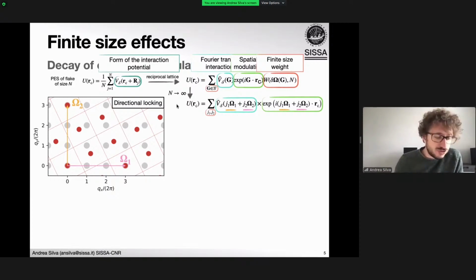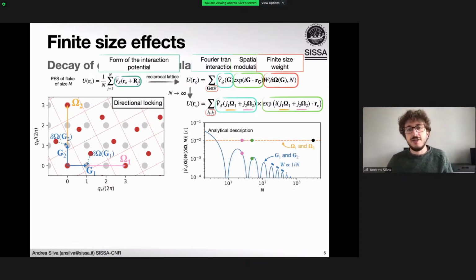So we have a superposition of different modulations. For example, we can check what happens to these other two substrate lattice vectors, so these other modulations. And we can describe analytically how these decay towards the infinite limit. We have a constant term here, which is the coincidence lattice vector, and a decay term, which won't be seen at infinite size, but still very much affects the behavior at finite size.